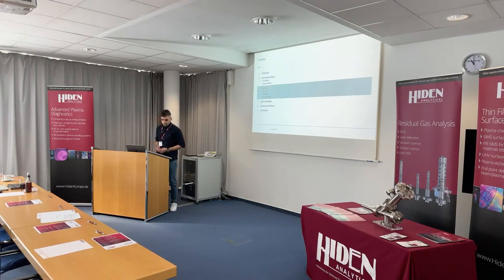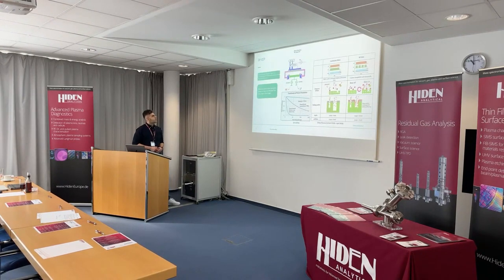Now we go to methods. Dual frequency CCP can generate continuous wave plasma and pulsed plasma. This is a chamber, LF power and HF power. The decay time constants for ions, radicals, and electrons are different when the plasma is off. So this helps us with etching profile. In continuous wave, you see the etching profile is different because of the opening here. But in pulse mode, because of the control over the ion per radical ratio, you will see this etching profile.